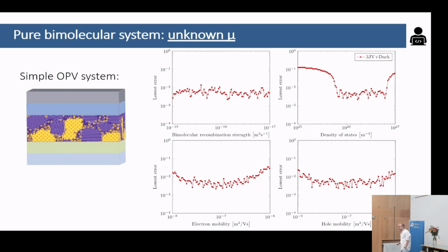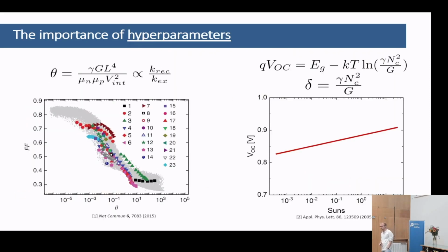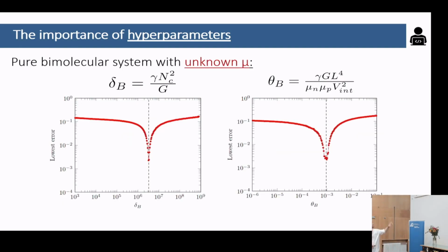However, you can work out those hyperparameter figures of merit that physically make sense. For example, this one relates to the fill factor and to the competition between recombination and extraction, right? So this is a very strong fitter. And you can define another one for the VOC on the right. And if you look at how unique your solution is with those figures of merit, you actually see that even if you don't know the mobility, you get a very narrow point, a very, very unique solution by fitting drift diffusion simulation to your JV.